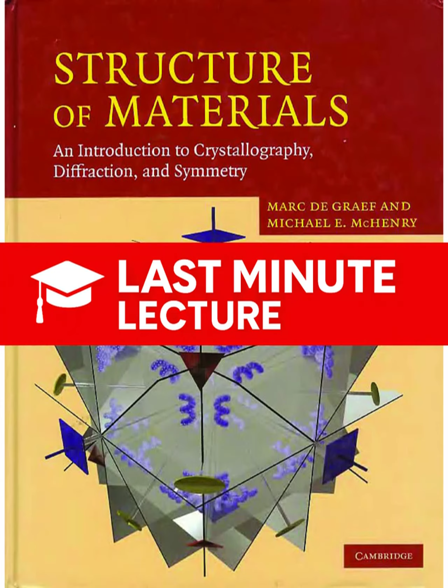Correct. So our atomic scattering factor, F, has to be corrected. We multiply it by this Debye-Waller factor, e to the minus M. This factor is always less than 1, which means thermal motion always reduces the intensity of the observed peaks. And the magnitude of that reduction M, what does it depend on? It's proportional to the mean square displacement of the atom from its ideal lattice site, and it's obviously very temperature dependent. Higher temperature, more vibration, bigger M, more intensity reduction.